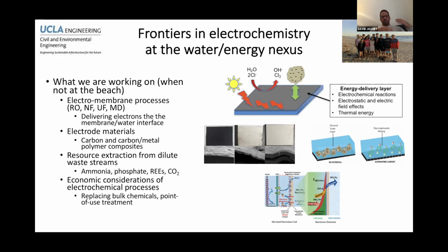So over the years, me and my group have developed a range of materials that meet those parameters, and they follow the traditional water treatment membranes. So we do everything from reverse osmosis membranes and nanofiltration membranes for desalination and water softening, and then all the way to ultrafiltration and microfiltration to remove things like viruses or bacteria, or pre-treatment for desalination. We also do quite a bit of work on thermal desalination technologies like membrane distillation. And those are really used to treat high salinity brines, so taking things almost to crystallization, to zero liquid discharge. And again, the overriding methodology and idea here is to be able to deliver energy, in this case electrical energy, electrons, directly to that membrane water interface. And you can really do a lot of cool things.